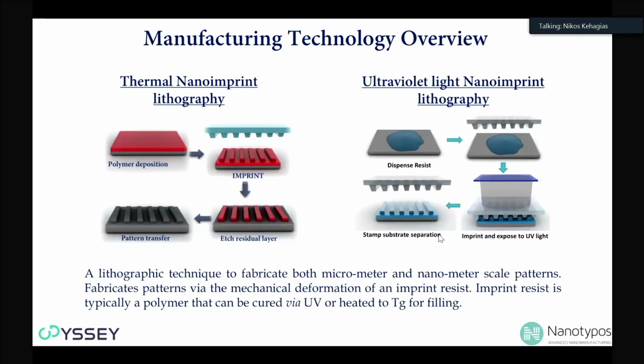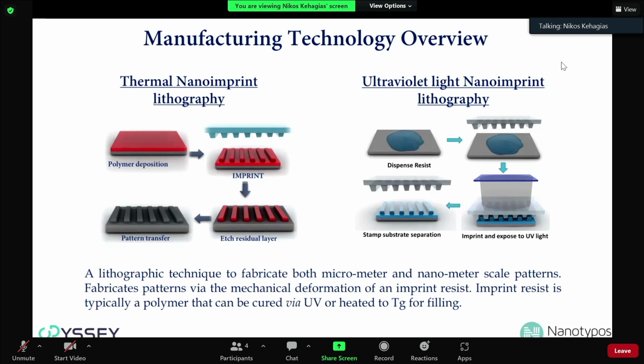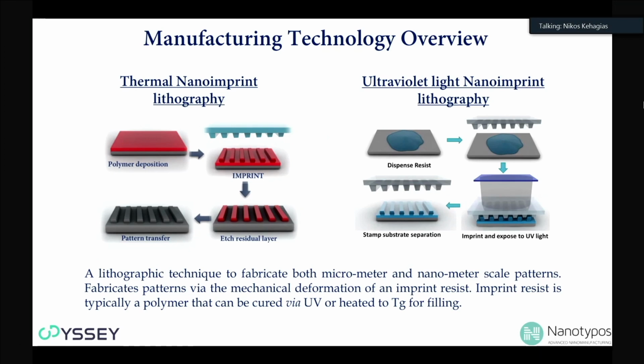So I will not dwell much on nano-imprint lithography. The basic idea is that we have a thin film, a thin polymer. It could be a thermoplastic or UV curable. We put it in contact with a stamp, with our mold, and once we either cure or heat to allow the polymer to flow in the stamp cavities, we can easily replicate the negative features of the stamp.